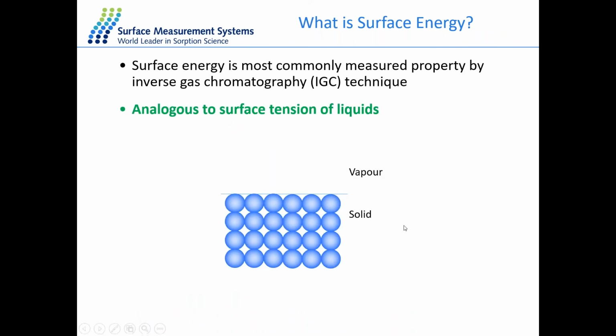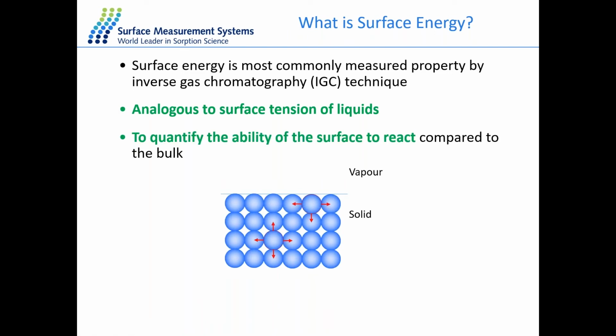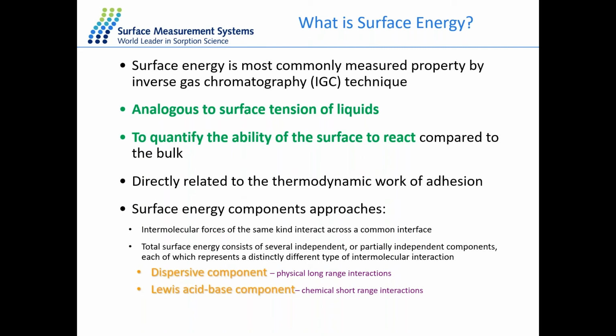So, like I mentioned before, surface energy is the most common property measured by the IGC technique. And what it is, it's analogous to the surface tension of liquids. This is the ability of the surface to react compared to the bulk. And in this case, we need two different components. One is a dispersive component, and this is in the form of maybe some n-alkanes. This gives rise to physical long-range interactions. We also need Lewis acid-base components, and this is in the form of your polar probes, and this gives rise to chemical short-range interactions.